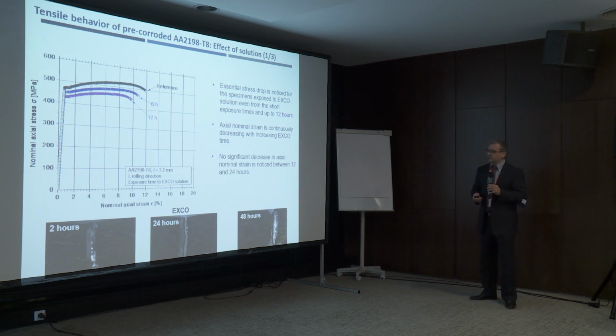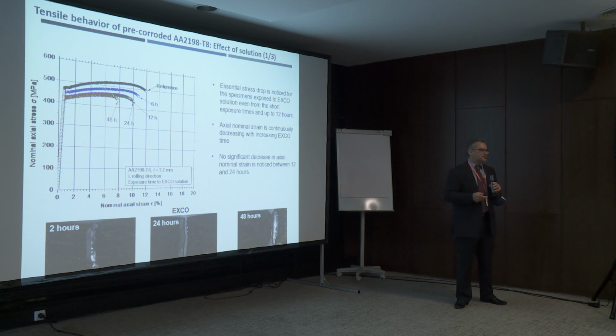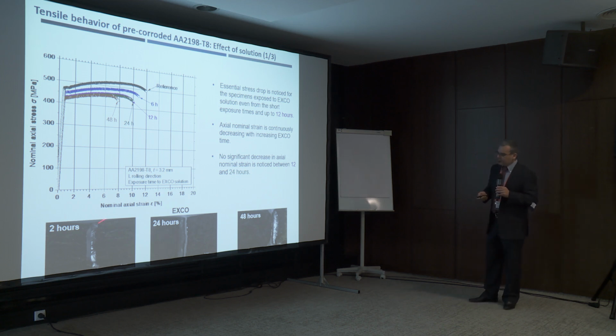These are the results after EXCO time. As you can see, after 2 hours or 24 or 48 hours, the material itself lost almost half of its ductility. So this is very critical for aircraft structures, because aircraft structures should be damage tolerant and should maintain their elongation at fracture.